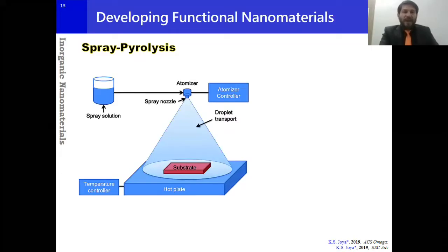Spray pyrolysis is a very easy and simple technique. Of course, it's not expensive, but it can be developed at home. At home means in the lab, students can develop it. You just need to heat the surface to a certain temperature, like I said previously, 600-700 degrees Celsius, and then you spray the precursor, whatever your precursor solution is, on the surface in a controlled way. The spray should be very fine, it should not be in the form of big liquid particles.